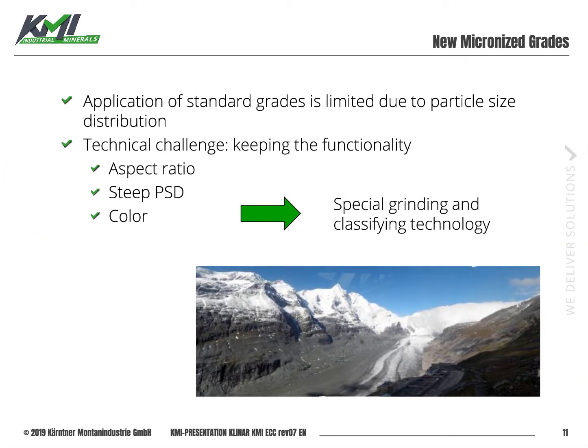But there is a limitation of the usage of standard grades, mainly due to the quite coarse particle size distribution. That means there is a minimum dry film thickness of not less than 60 to 70 microns to get a good corrosion protection when you use standard grades. And this was the reason for us to start a development of some new micronized grades, and the technical challenge was to find the right grinding equipment to keep the lamellar structure and keep the functionality of the coating.